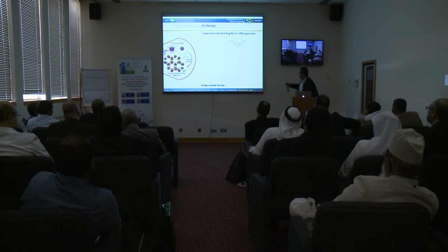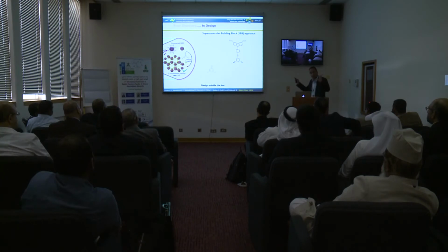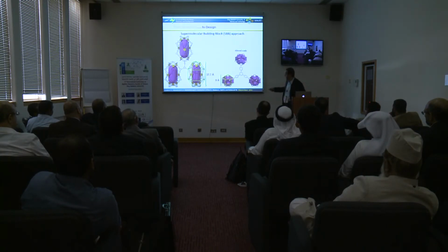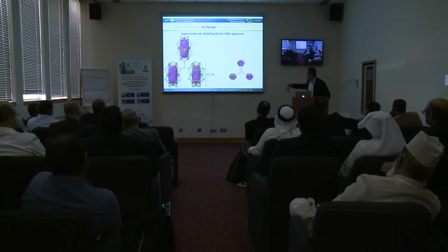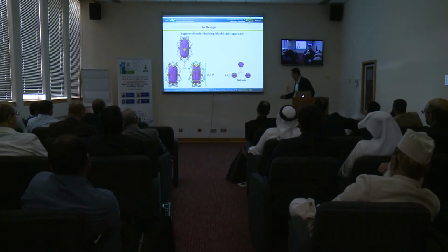So we're trying to make that ligand that has two 120-degree angles and one 90-degree angle, as you can see, a multiple-step synthesis. If we realize normally to have two 120-degree angles and 90, we should be able to make that structure, and sure enough, we get exactly the same structure, and this one was designed after this one was discovered. Then you can see here, this is the altered version of this. Now we create even more space inside this. So I think this is design.